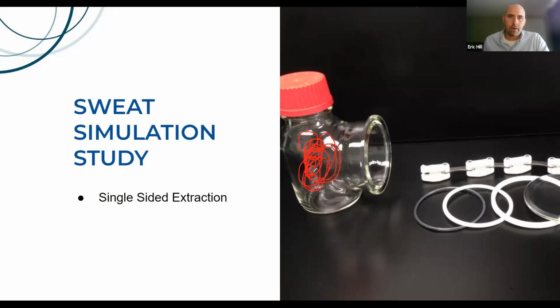We'd fill the vessel there. And then over here, you can see a glass, almost like a watch glass, far to the right. What we would do there is take the patch and stick it on that watch glass with the adhesive facing out. And then that watch glass would get clamped on the end of this vessel here, such that we can perform an extraction where the solvent in here is only going to contact the adhesive side of the patch. And so we get that single-sided extraction.